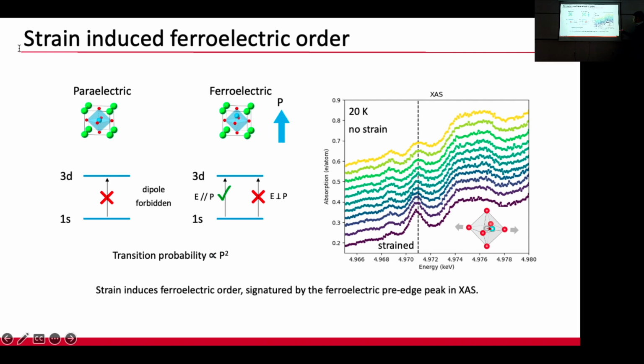Therefore, there is no such a peak and only a weak bump, and that is a higher order thing. You need a quadrupole transition, which is allowed, but that's a detail. So basically, in the centrosymmetric structure, this dipole transition is not allowed, so you don't see a strong peak. And when we stretch it, it breaks the inversion symmetry, and such a transition becomes allowed.